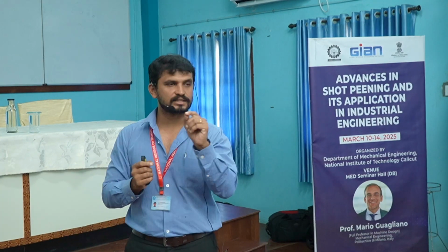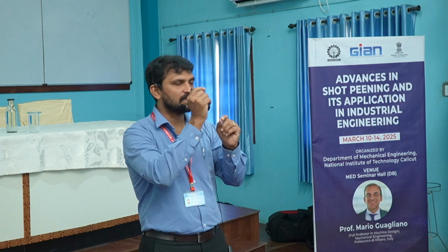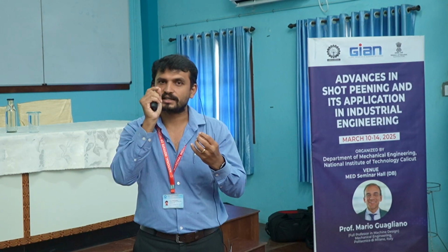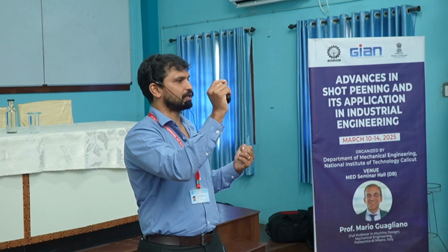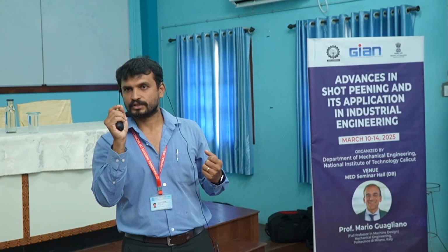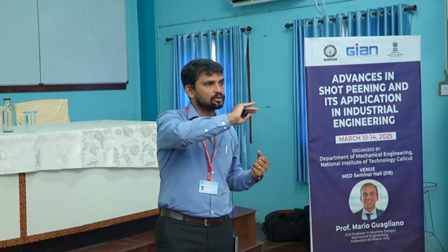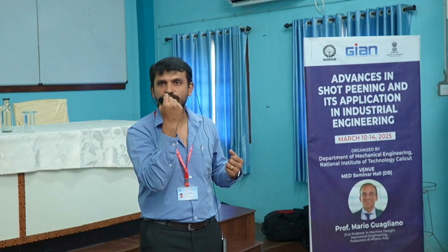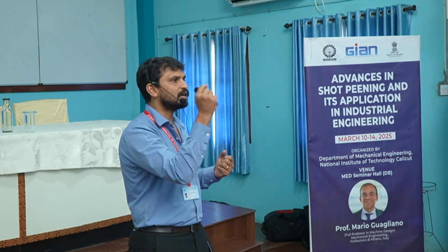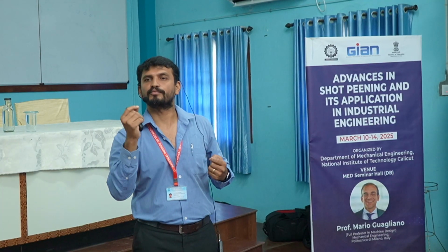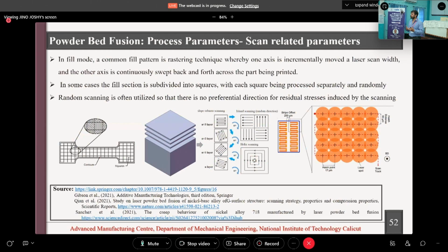Like you have seen in yesterday's first two classes, after the fatigue component has failed, they find out from where the crack was initiated, isn't it? Do you remember that figure? You have seen some sandmark or beach-like structures, and before that it all initiates from one point. So that unmelted powder point can be a location from where the fatigue crack might have initiated. In many literatures it is shown that the cracks propagate from these porous structures or even from these unmelted powder regions.